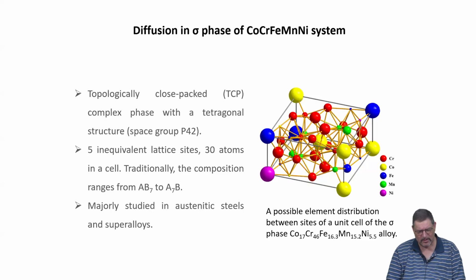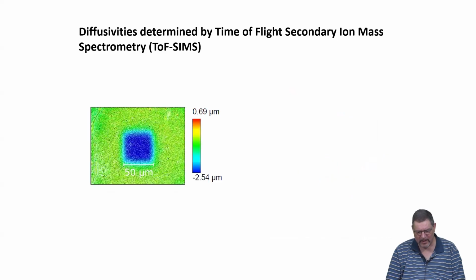There are 30 atoms in 1 unit cell, and compositions traditionally range from AB7 to A7B. Normally it's a binary phase that forms. This is mostly studied in superalloys and in austenitic steels, and again studied because people like to avoid it. Right. Here we just take it as a model system for a high entropy intermetallic phase, and here diffusion was determined by time of flight secondary ion mass spectroscopy. This is then showing you how such a measurement would look like.